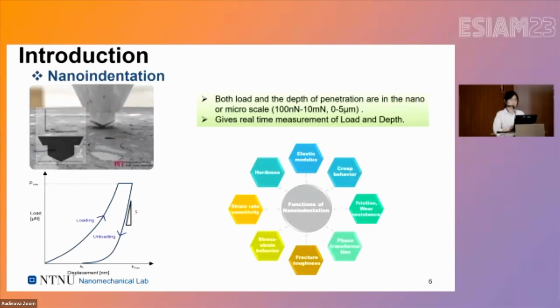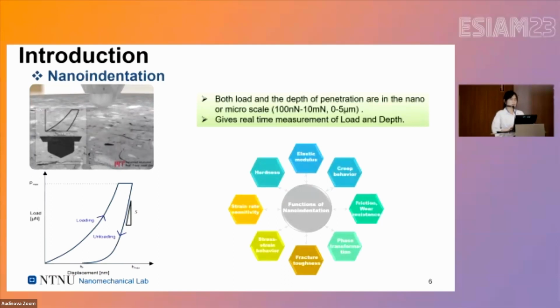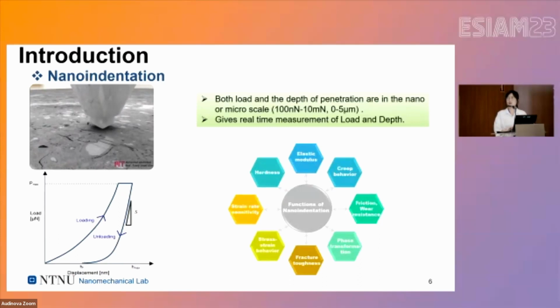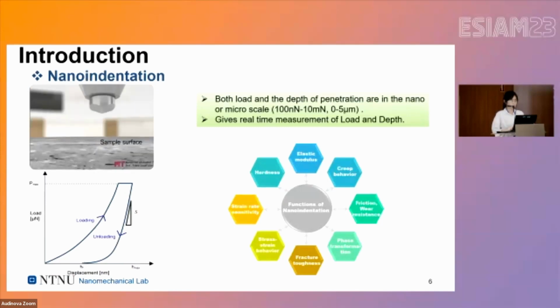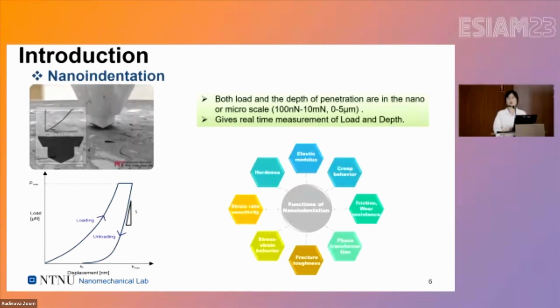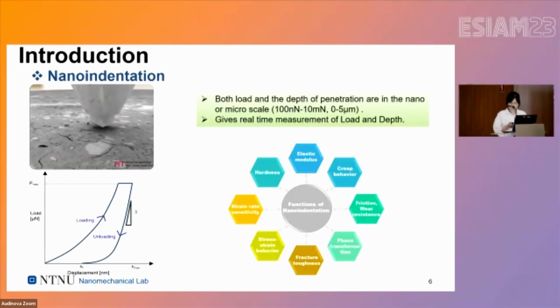So, a brief introduction to nanoindentation. The nanoindentation technique applies an indenter into the surface of the sample, with both the load and depth in the nano or micro scale. As can be seen in this image, the load and the displacement are recorded during the process, so it gives a real-time measurement of the load and displacement. From this load-displacement curve, we can analyze the mechanical properties, and the elastic modulus and hardness are the most commonly studied. Besides that, the creep behavior, strain rate sensitivity, fracture toughness, and so on can also be studied by this method.